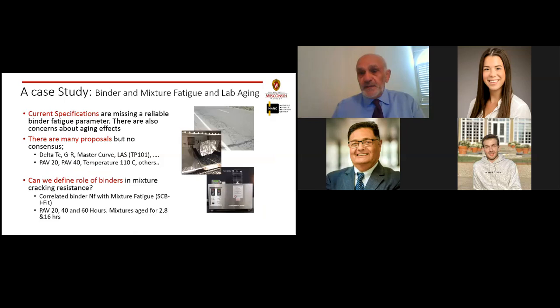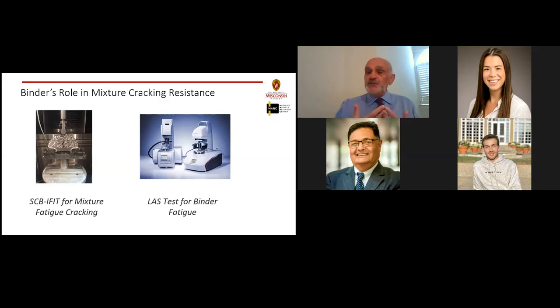There it is. So the motivation for the study is that there are many proposals for replacing the fatigue parameter in the specification. There is the delta Tc, the Glover-Rowe parameter, the master curve, and of course there is the LAS. We also talk about many different aging conditions and so on. So what we tried to do in this study is take the mixture I-FIT test and the binder fatigue test and try to correlate them, to see if there is a relationship and whether our hypothesis that large strains could give us a better indication of what's happening in the mix is true or not.